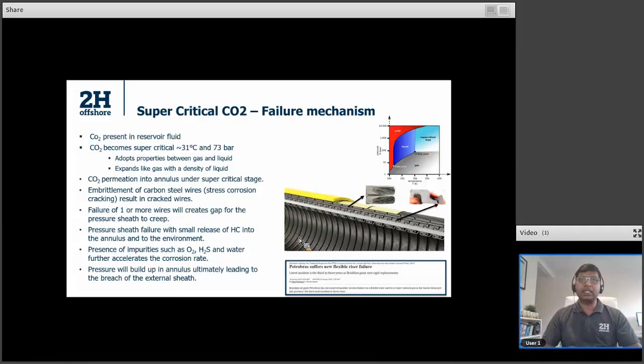A good example is Petrobras having to suffer a couple of incidents in the recent past continuously, and that's been attributed to the presence of supercritical CO2. And this is a mechanism which the industry is still trying to understand better, and how the carbon steel structures react to this kind of environment. And we'll see that as the industry progresses more and more into harsher environments, even within this region, I can say that some of the fields such as Prelude or upcoming fields such as Browse or Ichthys are all high pressure fields with very high temperature requirements and very high content of CO2. So there's a proper understanding that needs to go on with the effect of how the failure mechanism of SCCO2 happens for these carbon steel structures.